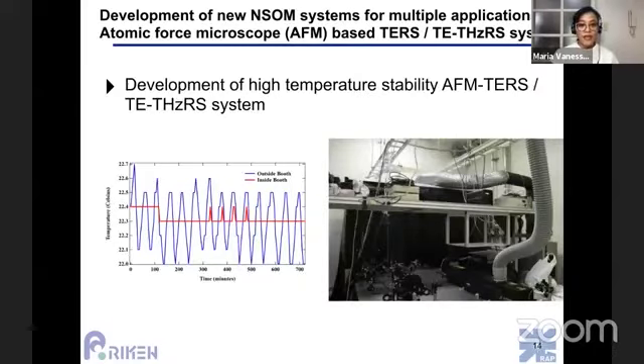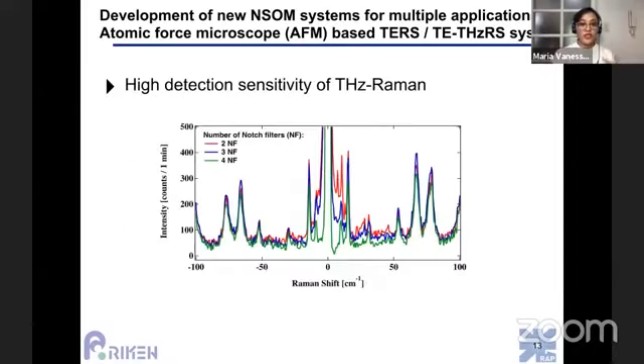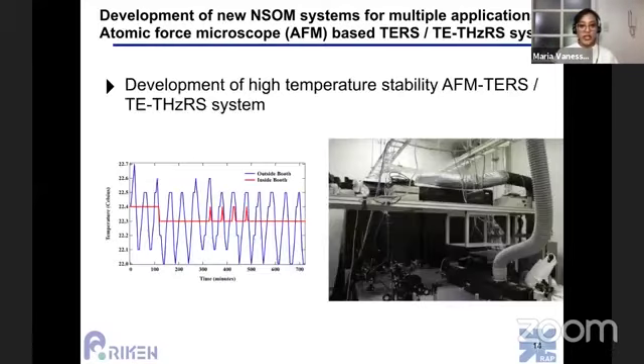And aside from that, of course, we want to have better chemical detection by improving the instrumentation, but we also want to have the system to be more stable to do better or even long-term measurements. Now, we also have a temperature booth installed wherein it controls the temperature, and the error is around plus or minus 0.1 degrees. So the red line is inside the booth and the blue line is outside the booth.